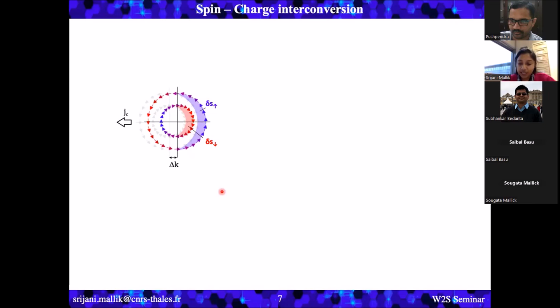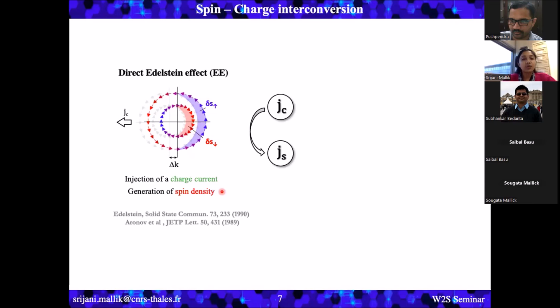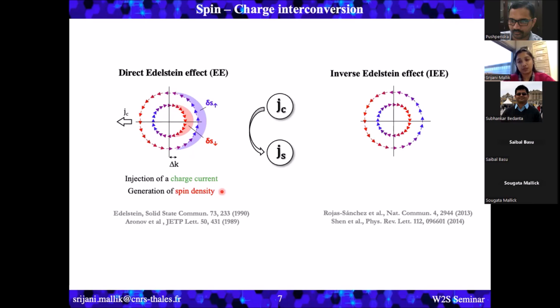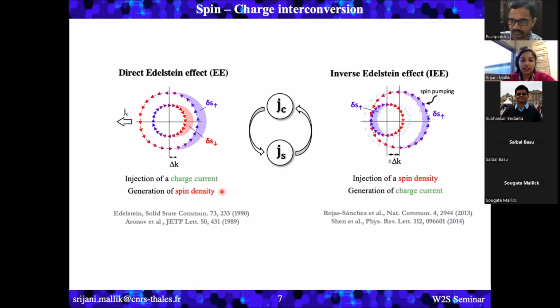So basically, by doing this, we can do a charge to spin conversion, and this is known as the direct Edelstein effect. And the reciprocal effect for this is known as the inverse Edelstein effect. And for this, in similar samples, instead of passing a charge current, now we inject a spin density, let's say by spin pumping. In that case, the Fermi contours will shift in the opposite direction and then there will be a charge current generated.